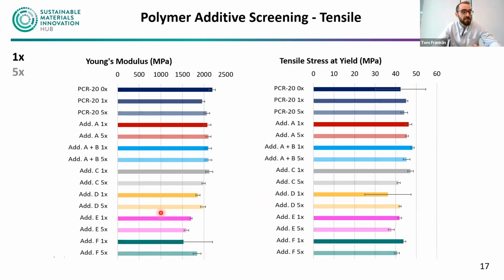Generally, these overall mechanical properties are lower, which again is surprising. These are compatibilizers. They're designed to at least maintain, if not improve, mechanical performance. So why they would be lower than our resins and our samples with no additive is a mystery, to be quite frank with you. It's a bit unclear. We're still trying to pick apart a lot of this data. So some quite interesting behavior.